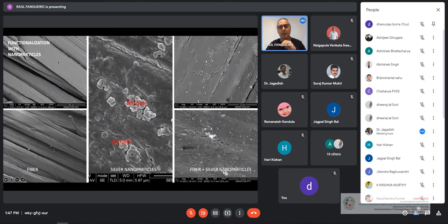But then we can place nanoparticles onto the surface of these fibers, for instance silver nanoparticles, to give these initial fibers, with intrinsic properties based on their polymer-based material, other functionalities. This functionalization with nanoparticles is very important because we can come up with different functionalities for this.